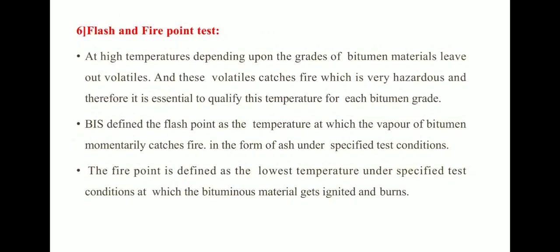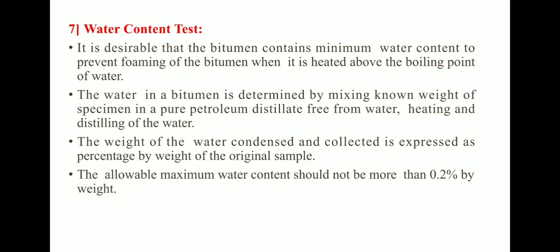The next test is the flash and fire point test. At high temperatures, depending on the grade of bitumen, the material releases volatiles that can catch fire, which is very hazardous. BIS defines the flash point as the temperature at which the vapors of bitumen momentarily catch fire in the form of a flash under specified test conditions. The fire point is the lowest temperature under specified conditions at which the bituminous material gets ignited and burns.